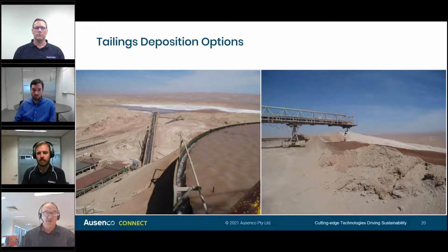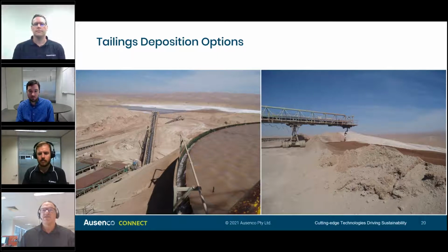The plant that you see here is one particular option where you could use a hydrocyclone and take the cyclone overflow to a thickener, and the underflow goes to a linear belt filter. This particular plant treats around 8,000 tonne per day of total tailings. The tailings are disposed separately as the thickened fines and a coarse fraction at around a 60 to 40% ratio, and the solids contents are approximately 60 and 80% by weight, respectively.